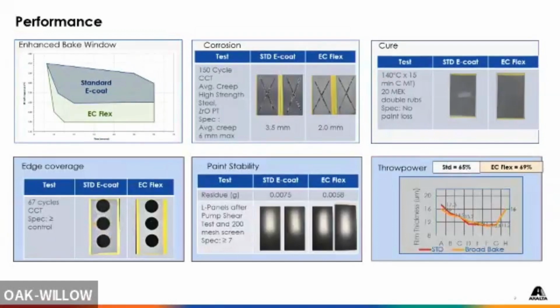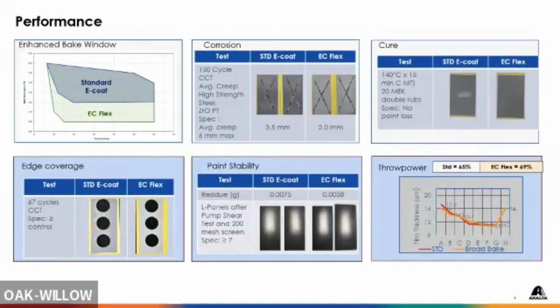The measurement of the ratio between the back panel and the front panel, which we call the A face, which represents the exterior, and the G face, which represents the deep interior, we want that to be over 50 to 60%. So that's what this is showing here. Again, because of the wet film resistance and the efficiency of the new material, I'm now able to get that A face coated to 16 microns very quickly, and then it gives me more time to get the G face coated, which means an increase in throw power.